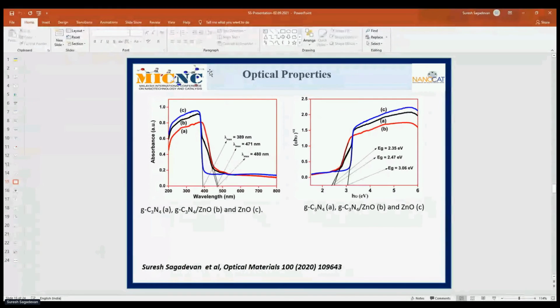We calculated the band gap value using the Tauc plot. You can see the band gap diagram for the three samples. The band gap value for graphitic carbon nitride, A in black, is 2.35 electron volts, the composite, B, is 2.47, and zinc oxide, C, is 3.06 electron volts. From these optical properties, we confirm that the shift towards the lower energy region for the composite indicates its sensitivity towards light, which in turn supports its enhanced photocatalytic activity.